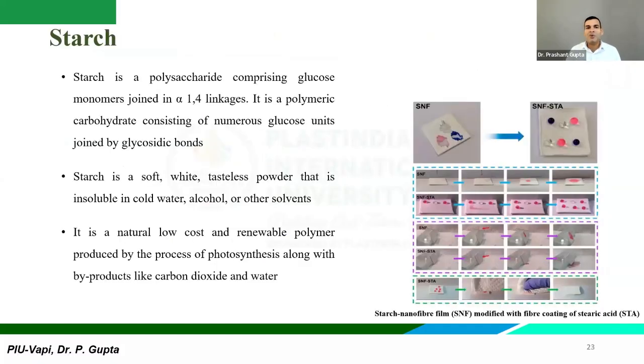So we talk about starch. This is another image where you understand what kind of features starch can have upon modification. So the left image that you see is a starch nanofiber film. You can see when you pour in three droplets which are transparent, pink and blue color, you would find that it will wet the tissue. But as soon as you treat this starch nanofiber film with stearic acid, you can see it behaves like a pearl. The contact angle significantly goes up, meaning you would not find any wetting.